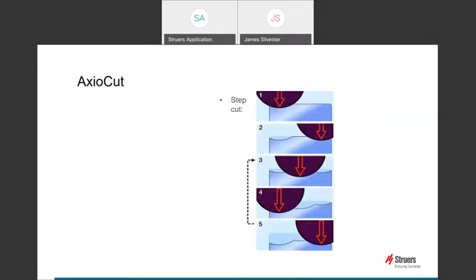AxioCut is an option available to larger cutting machines, the Axitom and the Magnetom. It is used for cutting extra large workpieces. On the Axitom, an additional 150 millimeters, which is 6 inches, of cutting capacity is available with the AxioCut step. This cutting mode allows cutting of deep workpieces when measured from the front of the machine to the back of the cut, and can be seen pictorially on screen.